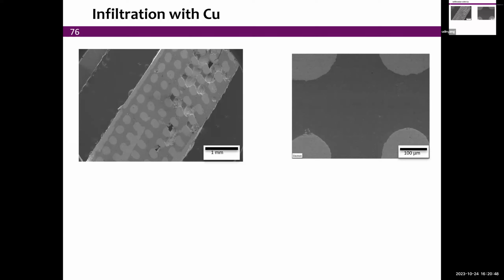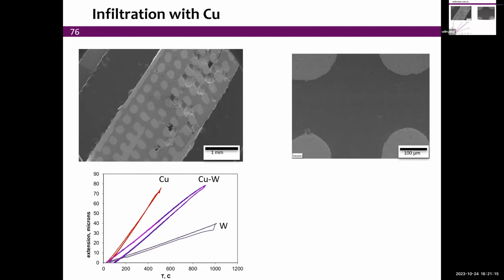And we don't have to keep just those empty lattice structures. We can also create composites. So this is a typical example where you now infiltrate the tungsten, which is brighter here, with copper. So liquid copper does not dissolve tungsten. It's completely compatible. It wets, and simply by dipping it in copper, you can now make a copper tungsten composite with this internal, very regular structure.